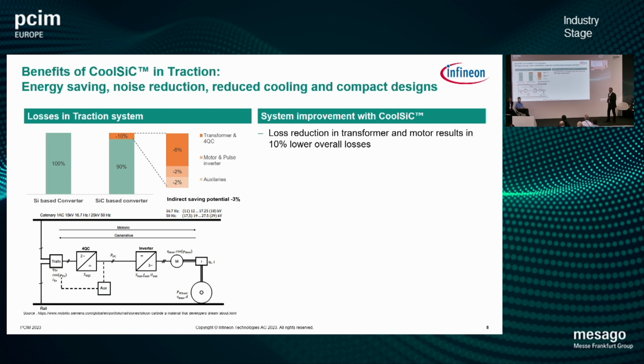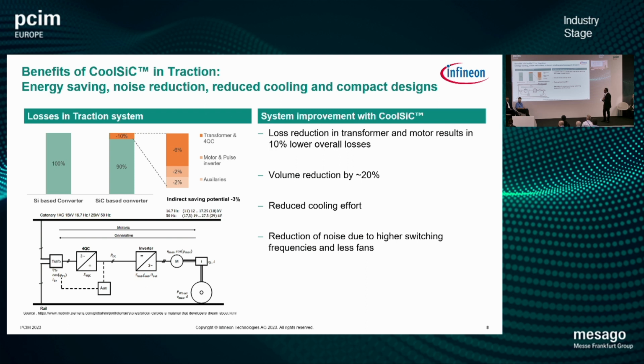Overall, what it clearly brings is 10% lower losses in the transformer and the motor, which results in a volume reduction of 20% because of the smaller size of the systems, and also a reduced cooling effort. Silicon carbide has very low losses, which means the cooling can be optimized to have smaller housings. And when you are operating at higher frequency, there is a benefit of reducing the losses and thereby also reducing the fan in the system. So you can go from a forced air-cooled system to a natural air-cooled system just through the lower losses of silicon carbide.